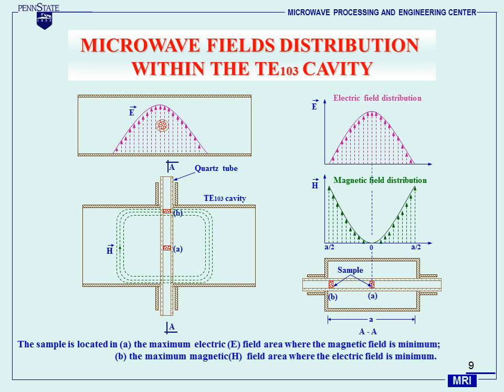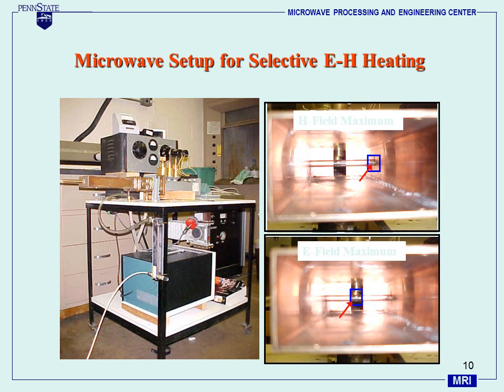Experimentally, it's very simple. There's a TE103, transverse electric 103 cavity, in which we set up a standing wave for the 2.45 gigahertz field. This is the regular home oven frequency, and you can locate samples at the maxima at A or B. And here's the experimental setup. It's one complicated gadget which you can buy for about 10,000 bucks, or you can build for 10,000 bucks. And there you can see the locations inside a silica glass tube holder in which we can control the gas.